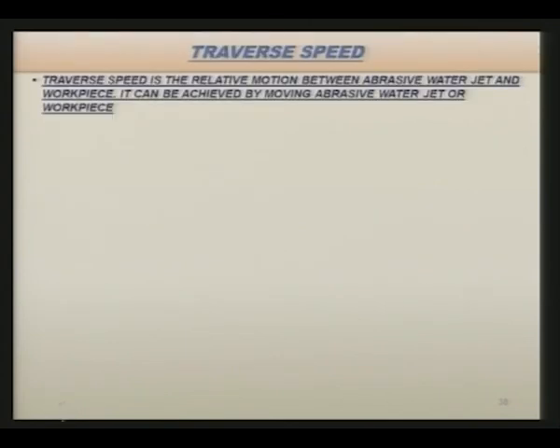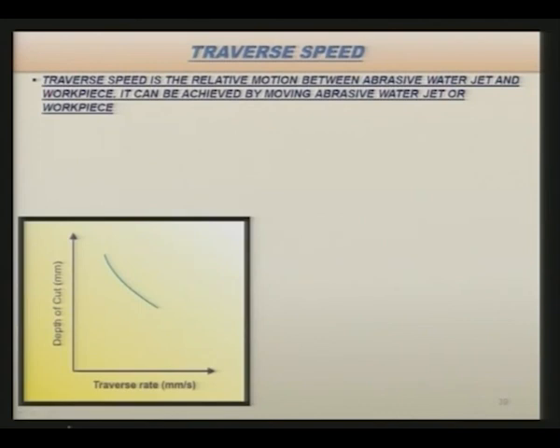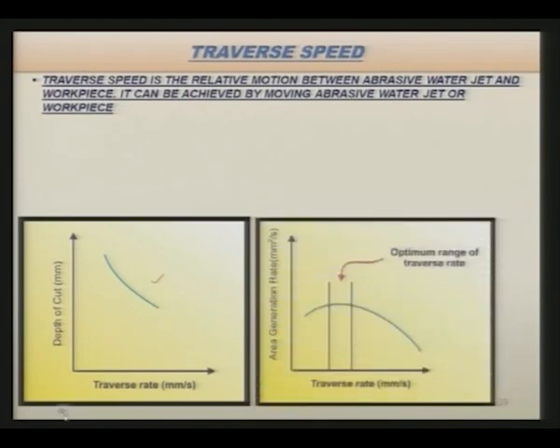Now, traverse speed is the relative motion between the abrasive water jet and the workpiece. It can be achieved by moving the abrasive water jet or the workpiece. If we see the relationship between traverse speed or traverse rate and depth of cut, this is the kind of relationship that we obtain: as the traverse rate increases, the depth of cut decreases. If you see here, as the traverse rate is increasing, the area generation rate is increasing, there is an optimum area generation, and beyond that it starts decreasing. Depth of cut decreases with an increase in the traverse rate, which may be within 10 millimeter per second.